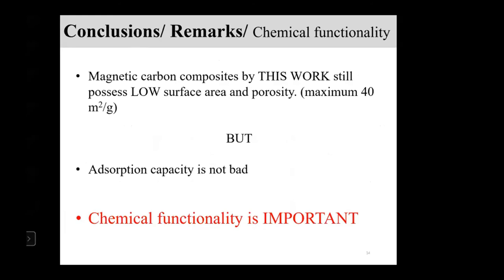So that means the porosity plays no clear effect. You don't need the material to contain a lot of surface area for adsorption if you have suitable surface functionality. In this case, chemical functionality is quite important. I just want to stress here that you don't need to have high surface area, but you have to make sure that your sample has available active adsorption sites to attach the pollutant molecule with a specific interaction. Okay, this is the example.